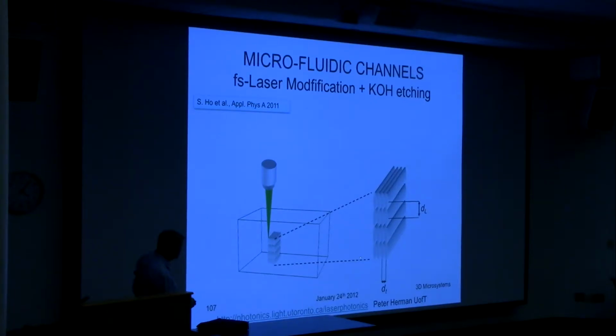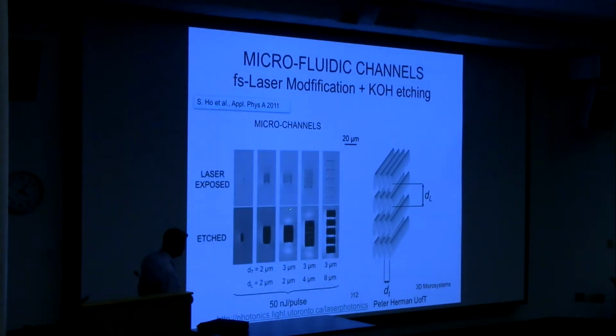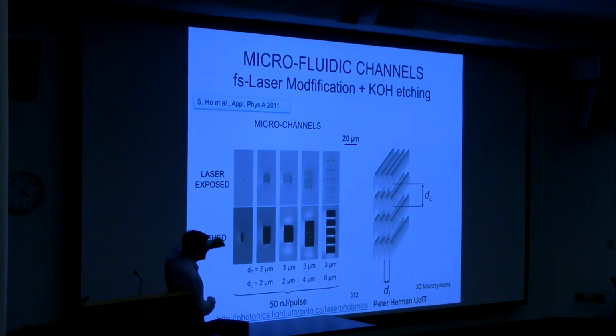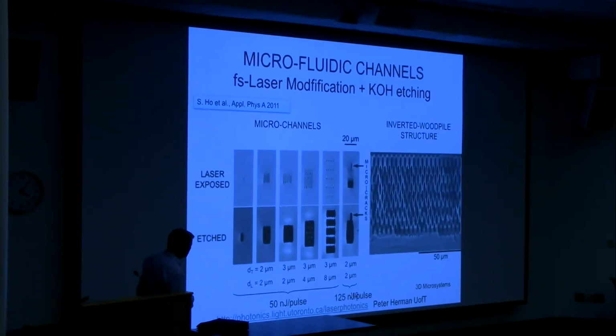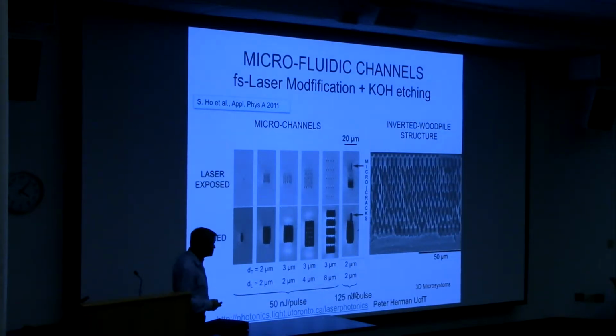If you make parallel laser tracks and then chemically etch them, you can control the shapes of devices that etch. So for example, here are the laser modification zones where laser tracks were in and out of the screen. After etching, you could open up rectangular structures as shown here. You have to align them appropriately to join, or maybe you want separate zones. But the neat thing is you can adjust the exposure parameters, and this is this inverted woodpile structure.